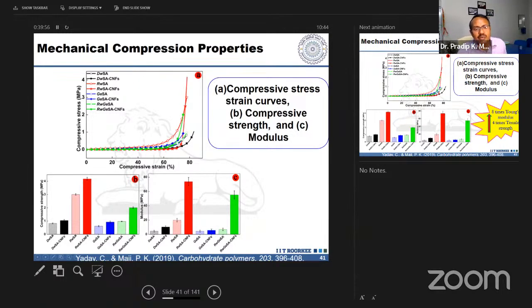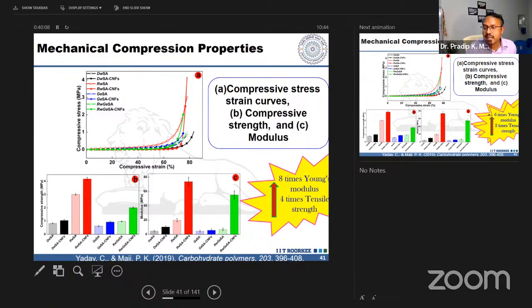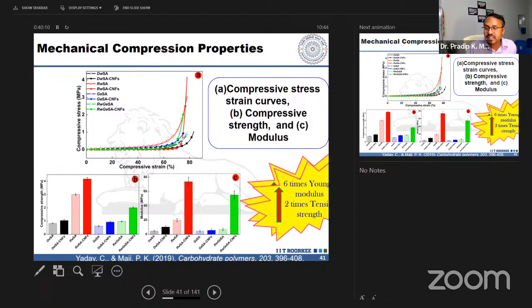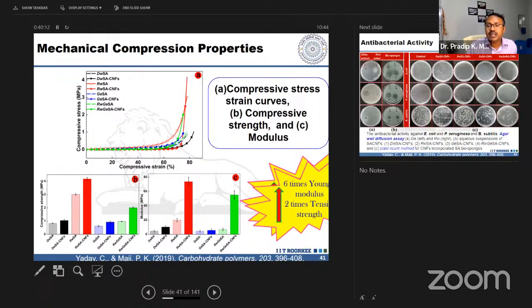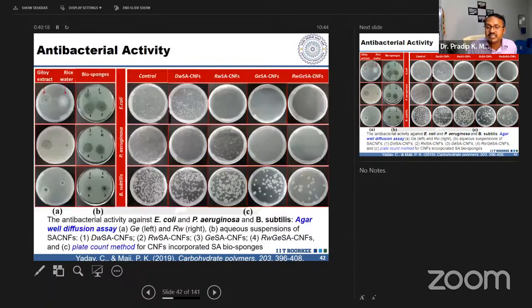We tuned the amounts of the other components, which is available in this particular paper, so you can go through it and get the composition of this material. There is an 8 times modulus and 4 times tensile strength increment. In another case there is a little bit of decrement, with 6 times Young's modulus increment and 2 times tensile strength increment.